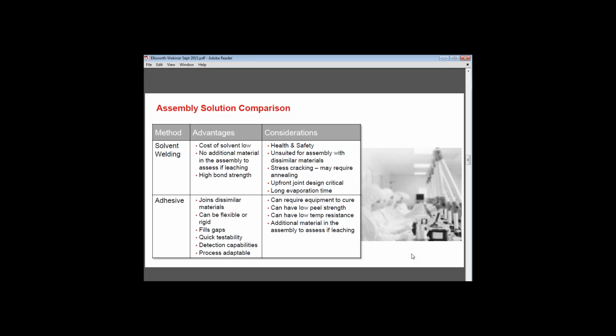The solvent prior to evaporating off the part could cause stress cracking that may require you to anneal the parts, or it could be seen further down the line in causing failures of the joint. The upfront joint design is critical. Most often with solvents, you need a very, very tight gap, either slip fit or press fit. And in some cases, there can be a long evaporation time in your process, so you might have to hold parts to go to the next step until that is complete.